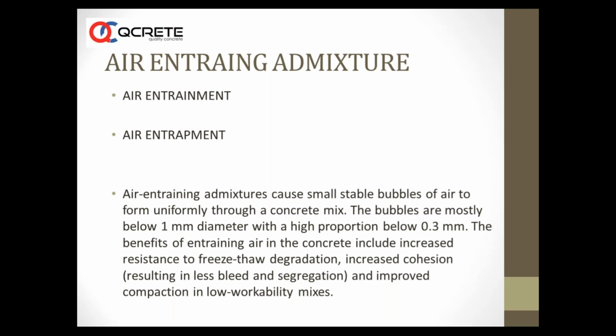So the difference between these two is that with air entrainment, the air bubbles are smaller, very small - largest maybe 1 mm or just below 1 mm, and then it can go up to 0.3 or 0.2 mm in diameter.